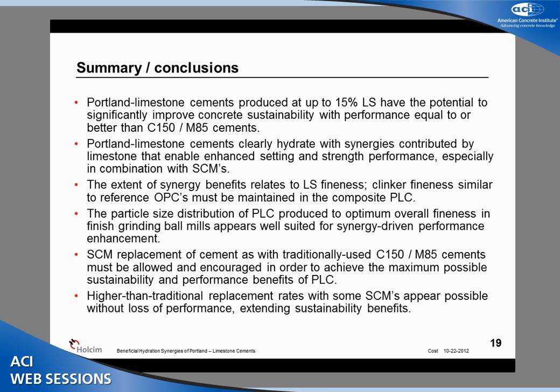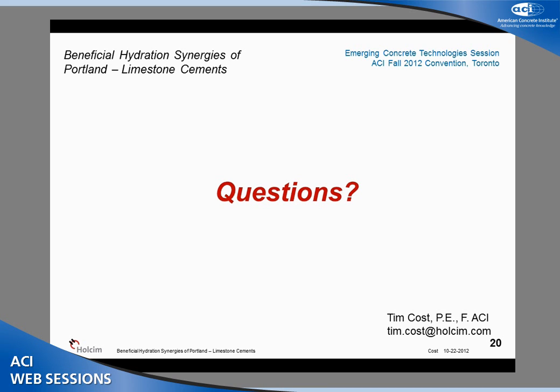If we're going to derive the benefits from this synergy, we must be able to use supplementary cementitious materials with Portland limestone cements, just as we would with ordinary Portland cements. And it might also be possible, as this work begins to suggest, that we might even further enhance sustainability, not just from the limestone component of the cement itself, but maybe even by increasing the replacement rate of supplementary cementitious materials. So that's where we are. We'll continue to work on this. There's some other research beginning by other researchers and universities as we speak that hopes to develop additional information, including things we might be able to do to cement chemistry to better capture these synergies of hydration.